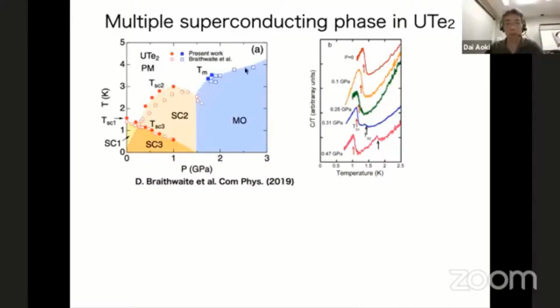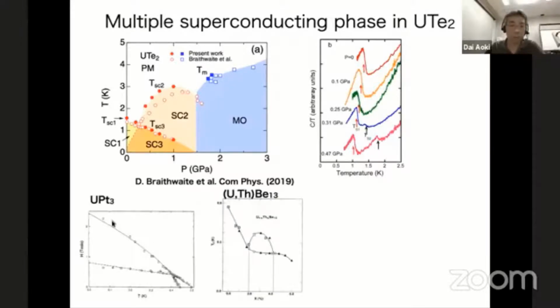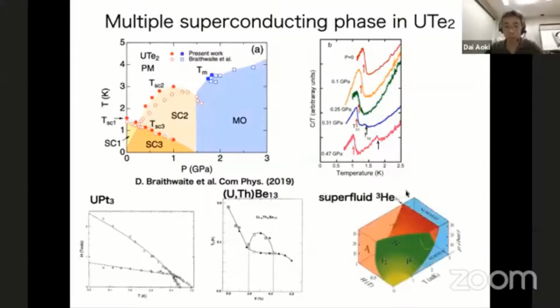Then another ordered state appears, and this is probably a magnetic ordered state. And this kind of multiple superconducting phase is well known in UPt3, for example. Here you can see H versus T, where there are A, B, C phases, and also in uranium beryllium-13 doped with thorium. You can see the multiple phases. And of course, we also know that superfluid helium-3 shows multiple superfluid states like this. So this multiple superconducting phase is a strong indication for the spin-triplet state.